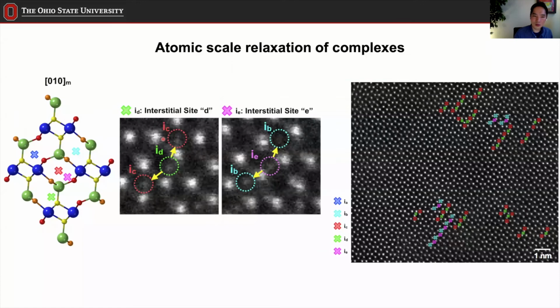All right. Okay, so that's about the formation of complexes. Now, some extra information that I can also show you is the formation of this other type, which we named as interstitial D site intensity, as well as the interstitial E site. So now these weren't considered before in any of the DFT or atomic scale models, but there was some extra intensity showing up, so that we saw them. And then, interestingly, whenever this ID site intensity is there, they were always paired with 2 IC site intensities. It was always the case. And in the same way, when there was IE site intensity, they were always paired with 2 neighboring IB site intensities. So this is kind of like looking at bigger scale complex formation.